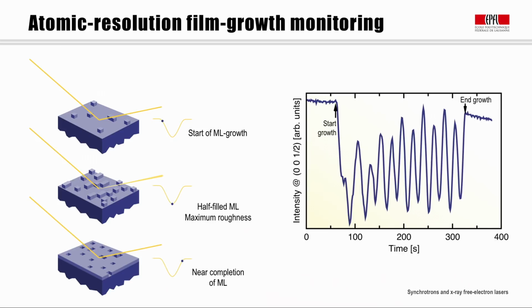The decrease in reflectivity with surface roughness can be exploited in situ X-ray reflectivity experiments in order to monitor film growth. If the film grows in a monolayer for monolayer manner, this is called Frank-van der Merwe growth, then the roughness will vary sinusoidally, being maximally rough when each new monolayer is half complete. So by monitoring the reflectivity during growth, the growth can be followed monolayer for monolayer.